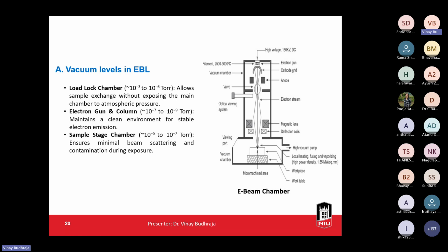Electron gun and the column. Over there, 10 power minus 7 to 10 power minus 9 torr. So it's a very, very high vacuum. This maintains a clean environment for stable electron emission. Sample stage chamber maintains 10 power minus 5 to 10 power minus 7 torr. This ensures minimal beam scattering and contamination during exposure.